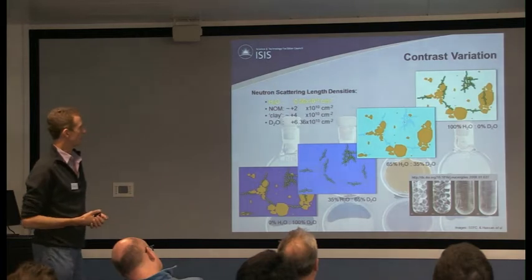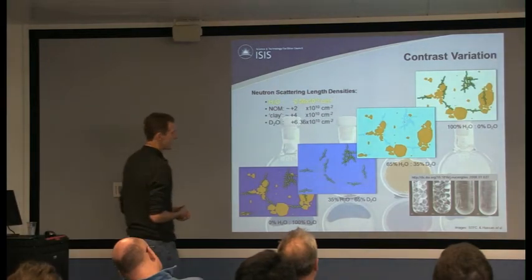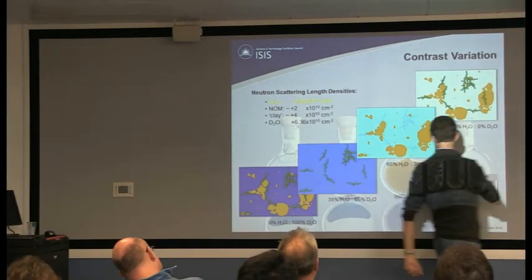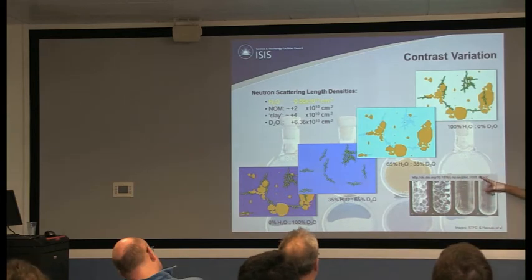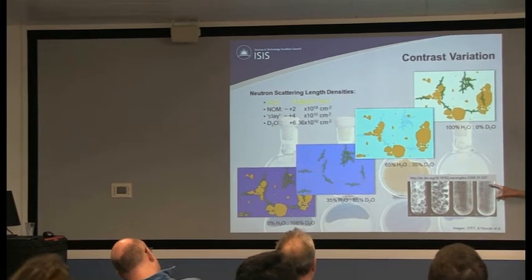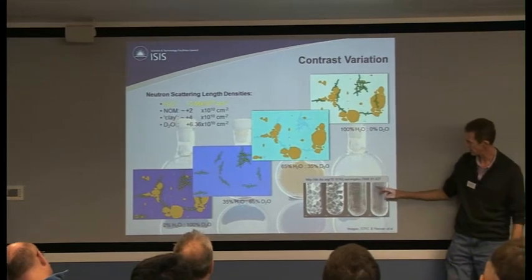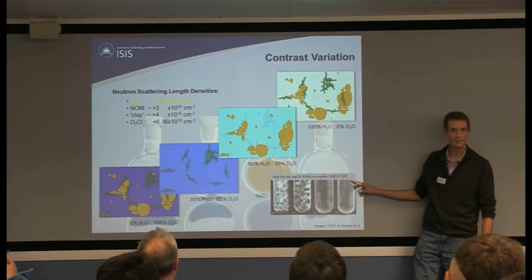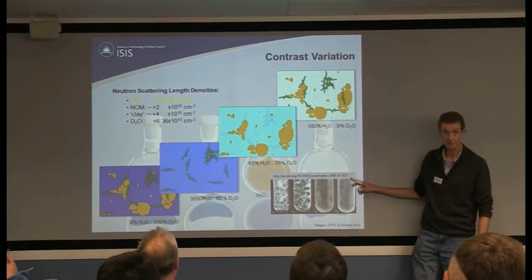I mentioned the technique of contrast variation. That's basically the neutron analogy of doing refractive index matching. Take a collection of glass beads in air, you can see them easily. You put a liquid in there, they start to go a little fuzzy. If you change the liquid so it has a refractive index similar to the glass beads, they start to disappear. And if you really optimize the matching of the refractive index, they completely disappear.